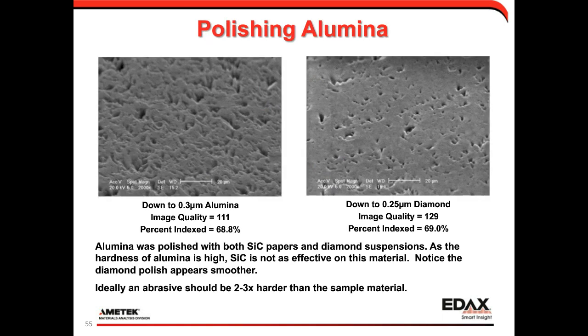Now what I want to show are some of the off cases, where we want to do something a little bit different. This is just an example of an alumina sample. Alumina is a ceramic. It's obviously a lot harder than the metals. It doesn't deform as ductilely as a metal would. So what I did here is, on the image on the left, I polished it down using 0.3 micron alumina. So I'm polishing alumina with alumina. And on the right, I polished it with diamond. Diamond is a little bit harder than alumina.